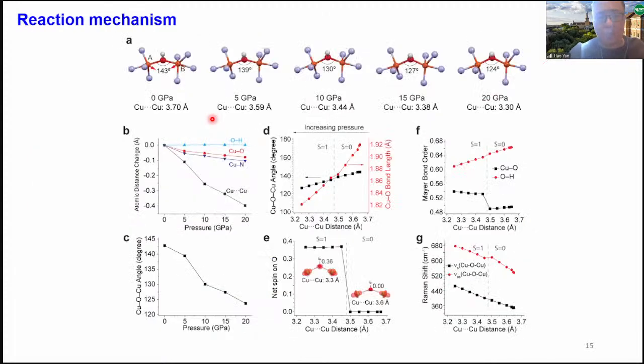Let's talk about the mechanism here first. What we think happens, and this is supported by DFT calculation, is that the uniform isotropic pressure generated in the diamond cell induced some highly anisotropic deformation in these molecules. In this case, it's bending the copper-oxygen-copper bond angle, and that bending weakens or decreases the covalency of the OH bond while bringing a pyridyl arm closer to the hydrogen, and this leads to a proton transfer.